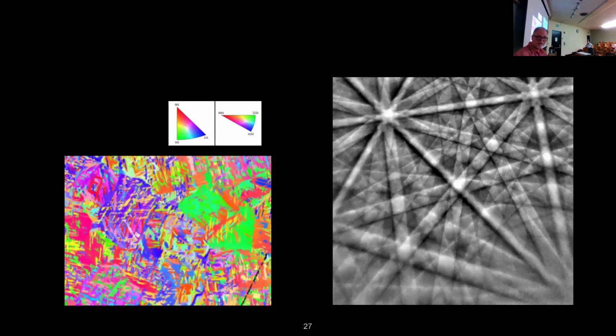And so this is an older IPF on the left side. So it's actually a metallurgy sample. It's additive manufactured titanium 6-4. And it's, I'm going to call it kind of a mess. You can see my mouse cursor. You can see there's like this black scratch here. That's actually a scratch in the material from the polishing. We did not do hydrofluoric. Normally you would do a little bit of hydrofluoric for polishing this, but not in our lab, not on a spinning wheel, no.